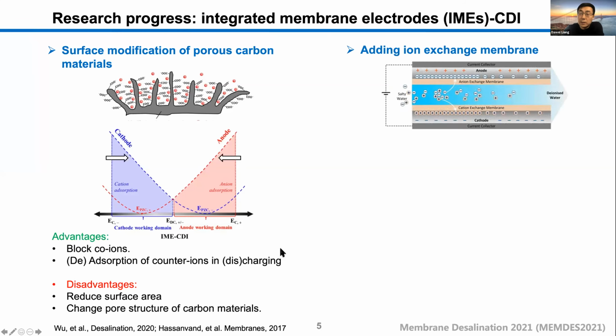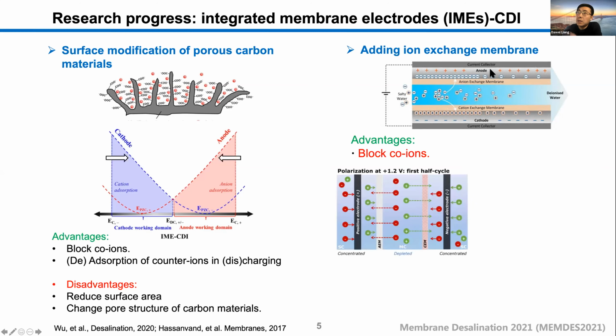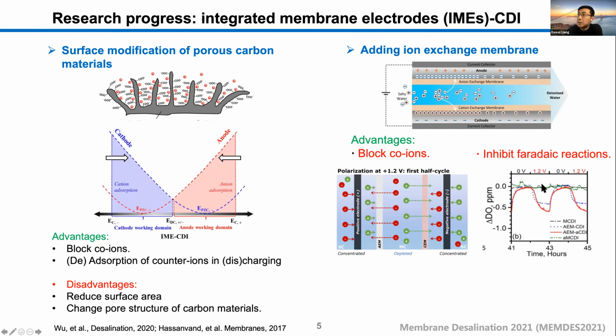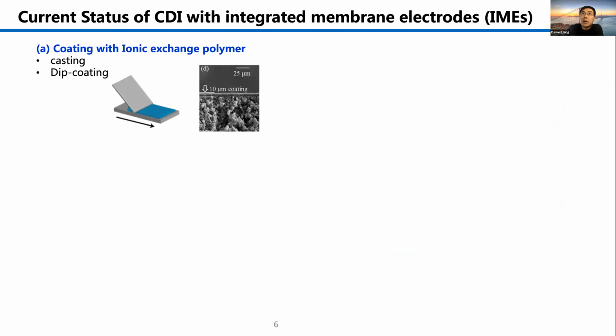The next approach is to add an ion exchange membrane. It has some advantages. First, it blocks the co-ion completely and also inhibits the Faradaic reactions. You could see the ion concentration in the solution does not change seriously when the membrane is involved. But the disadvantage is that if you use the membrane, you increase the cost and also increase the internal resistance.